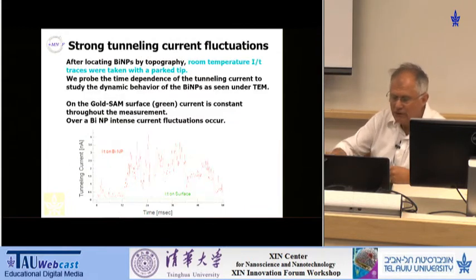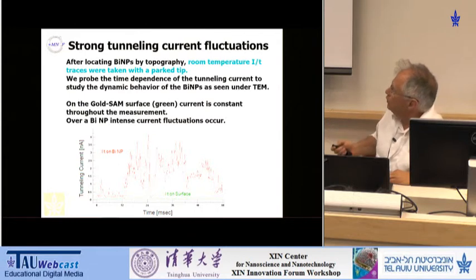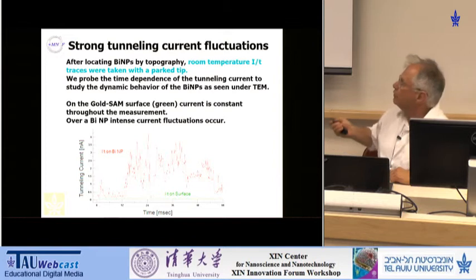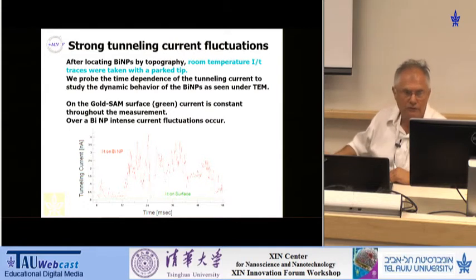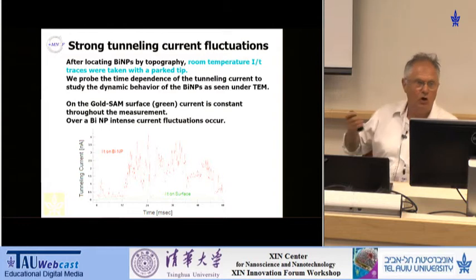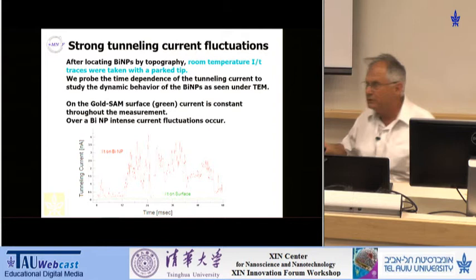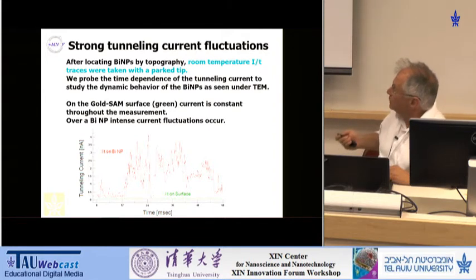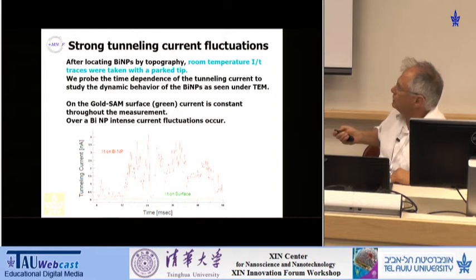So we set out to learn the properties of such nanoparticles, and what we saw is that when we sit on a single nanoparticle and record for a long time the current that passes through it with a fixed voltage, the current is very chaotic. It changes in orders of magnitude up and down. So this can signify two things. Either that we are extremely bad experimentalists, or that it indeed reflects the properties of the nanoparticle. To show you that we are considerably good experimentalists, if we make the same experiment on top of a gold surface, the current is very stable. Actually, this is a fingerprint of a good apparatus. We have built this apparatus. It's quite good.